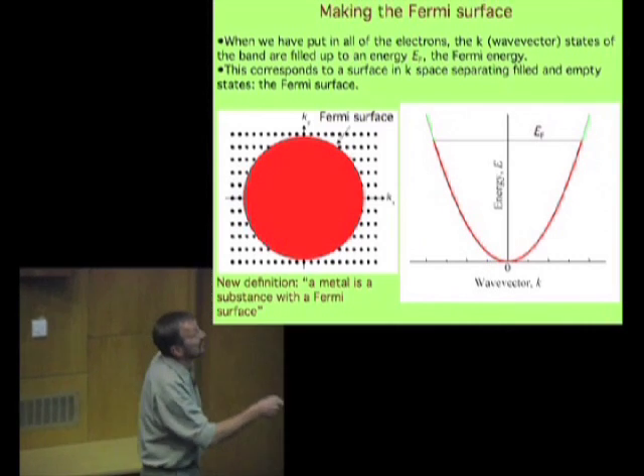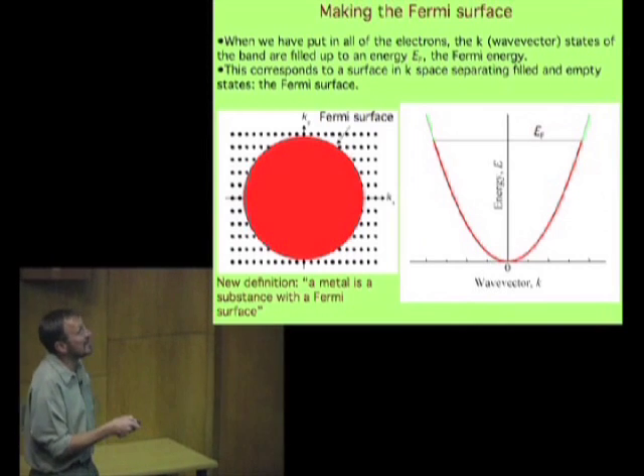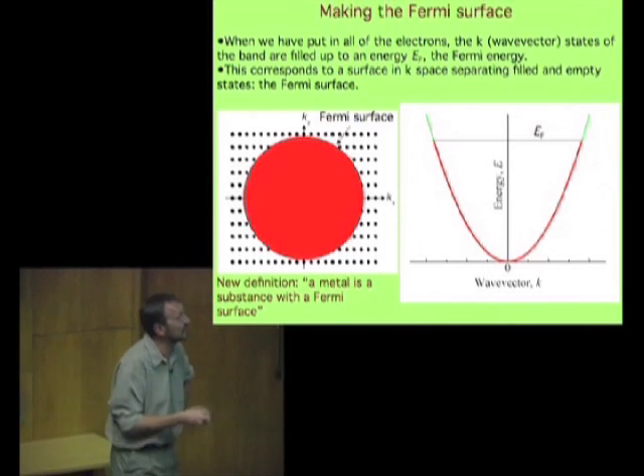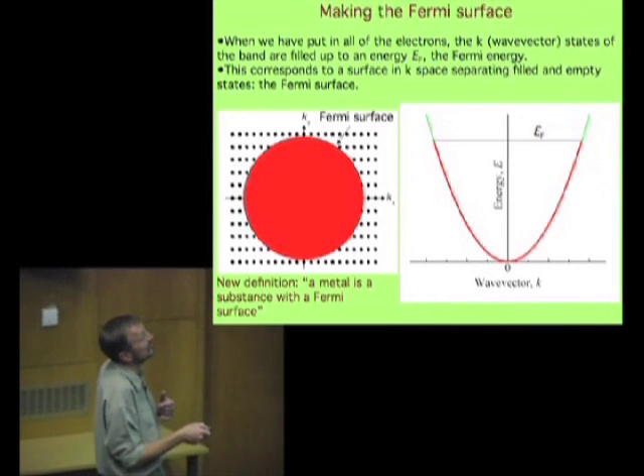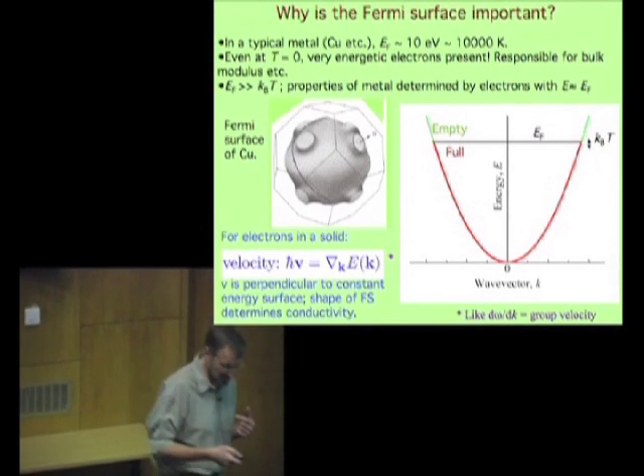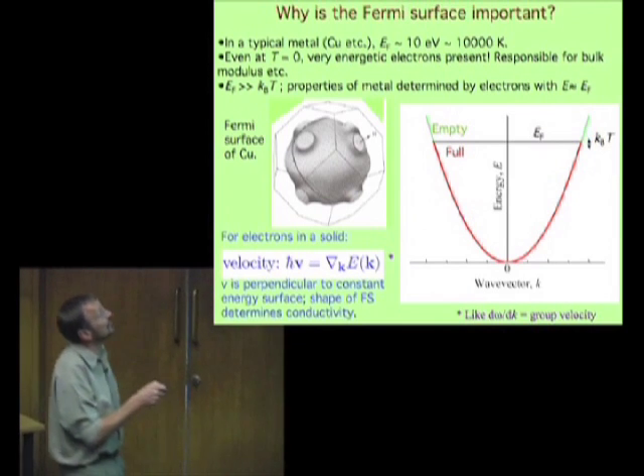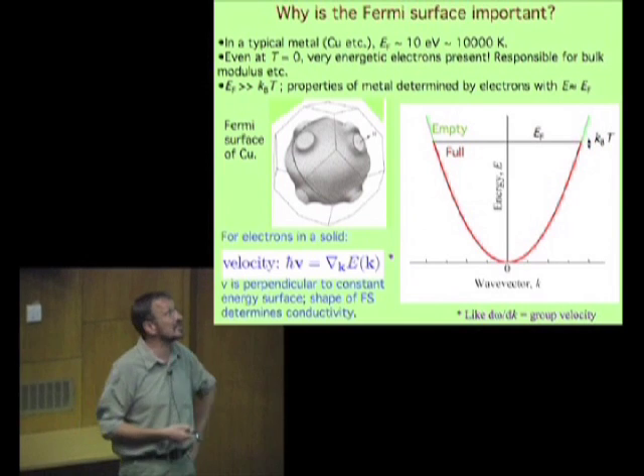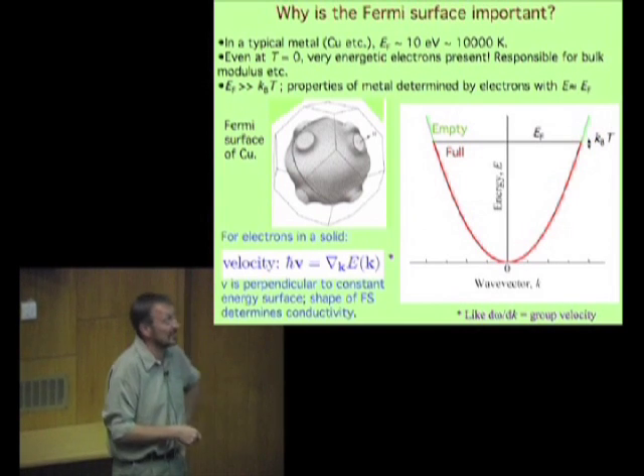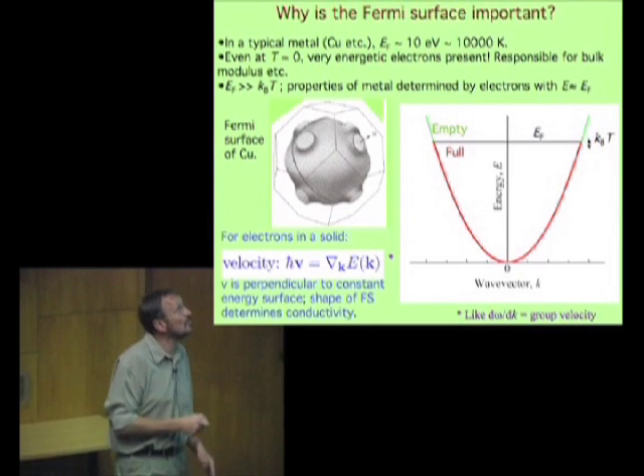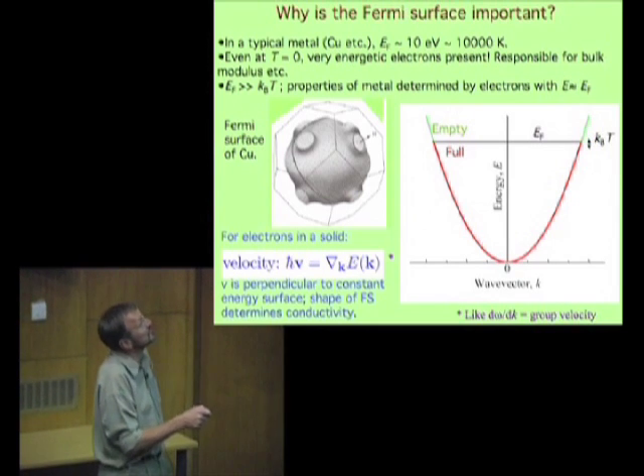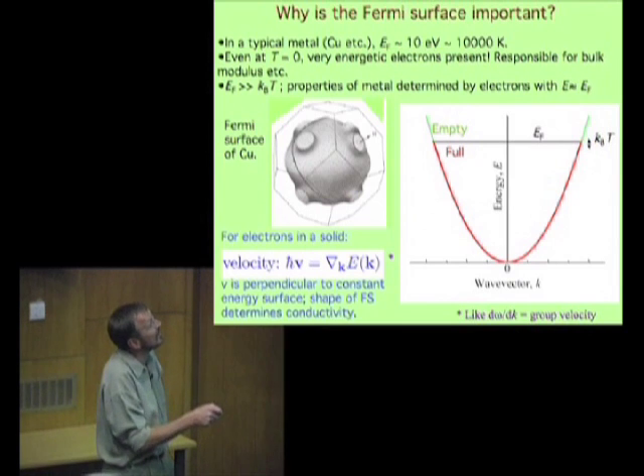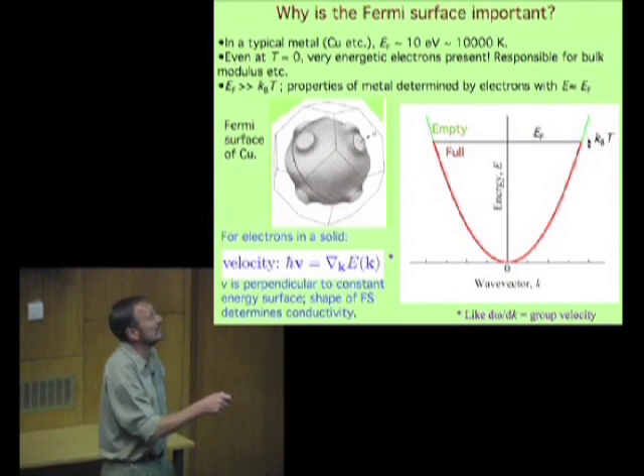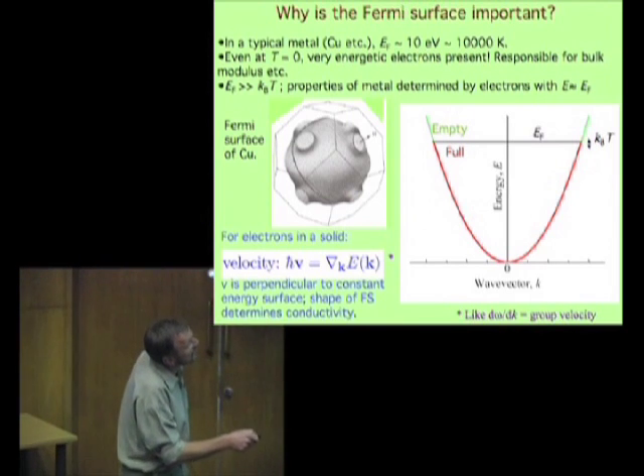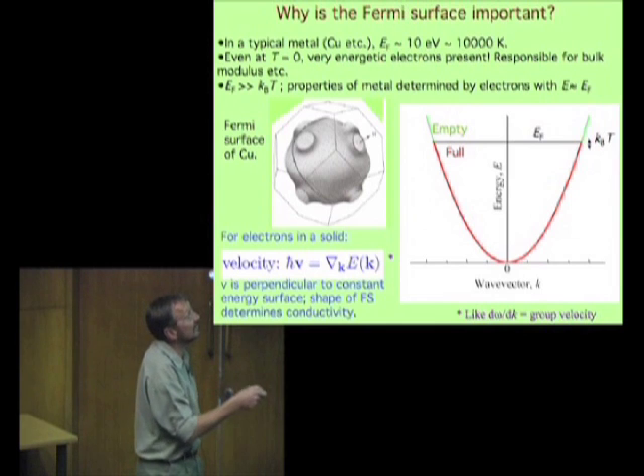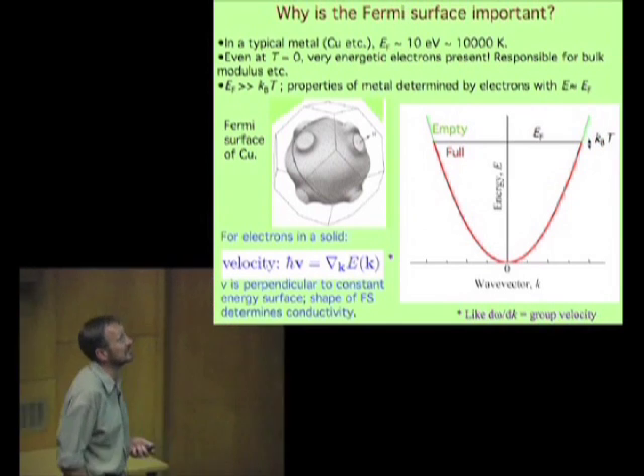So this Fermi surface is our definition of a conventional metal. A metal is a substance with a Fermi surface. I have no idea who coined that, but many people have used this in their textbooks like Kittel. So why is the Fermi surface important? Well, in a conventional metal, like copper and things like that, the Fermi energy is around 10 electron volts, or tens of thousands of Kelvin. And even at zero temperature, this is a picture of the Fermi surface of copper, we have these very, very energetic electrons on the surface of this thing. The reason being that all the states below them in energy are full. So they cannot get down to any lower energies because of the Pauli exclusion principle.